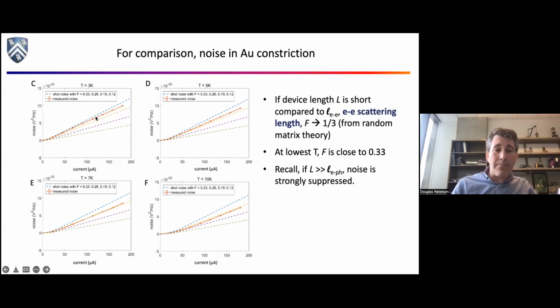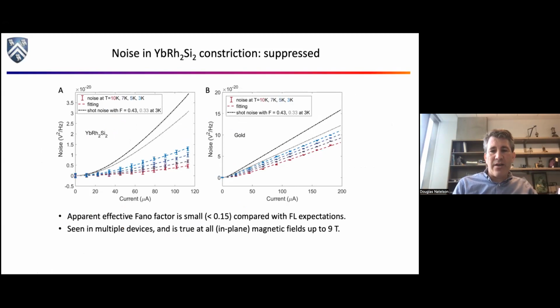Now, in this case, as I warm up, the Fano factor does go down a little. It goes down a little because in gold, you expect the phonons to be important. By the time you get up to 10 Kelvin, you expect scattering off of the lattice and energy loss from the electrons to the lattice to be detectable. Right. So let's put all these things together. Here's the ytterbium rhodium 2 silicon 2 case. Here again is √3/4 and 1/3, and here's all the data with error bars for the ytterbium rhodium 2 silicon 2. It's all the way down here. For gold, it starts out close to 1/3 and goes down a little bit.